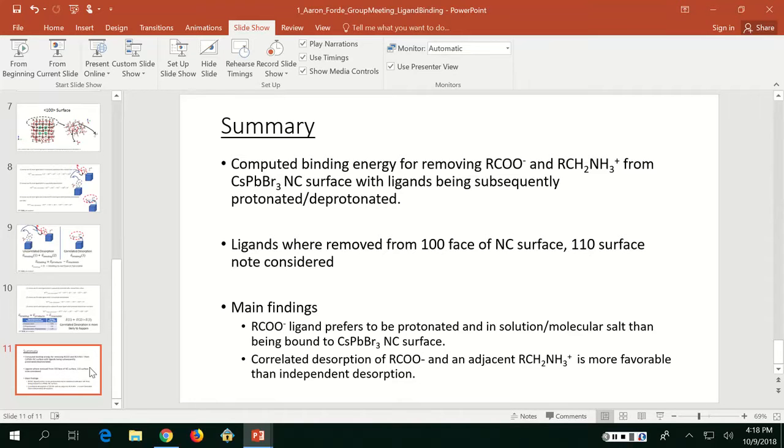There are millions of different ligands in organic chemistry, so why use exactly these two? Because the precursor is a lead halide, and they found that the only way to dissolve it is if you have both the amine and this type of ligand. If you only include the oleic acid, you can't dissolve the precursor.